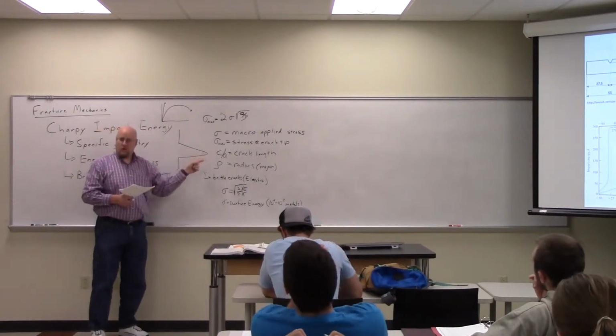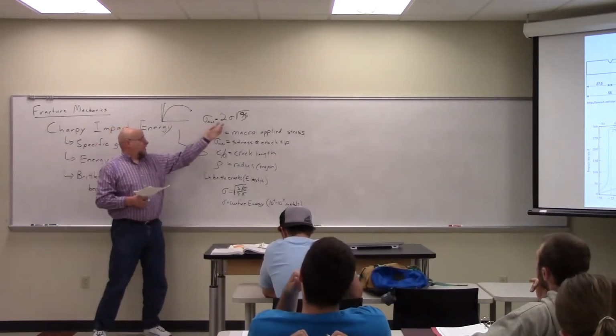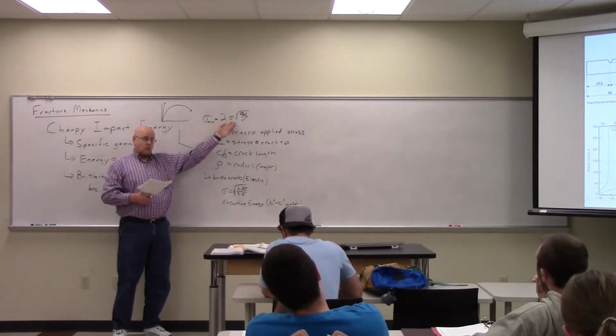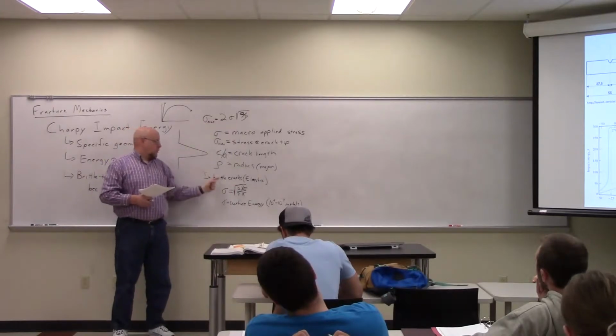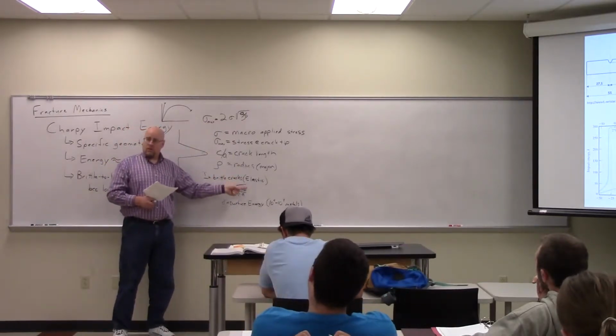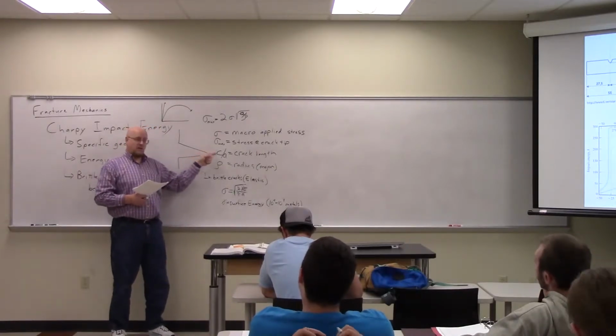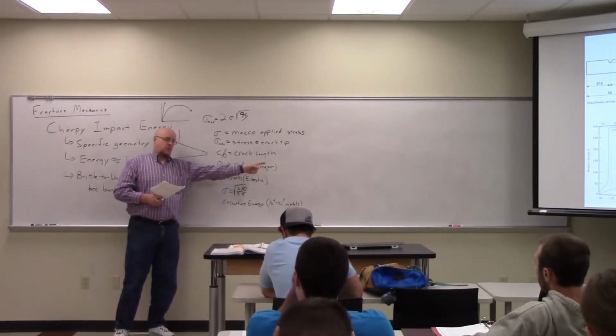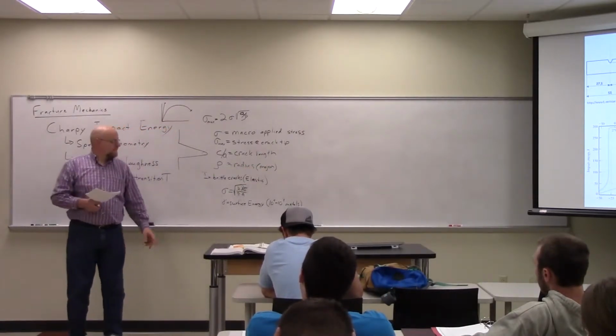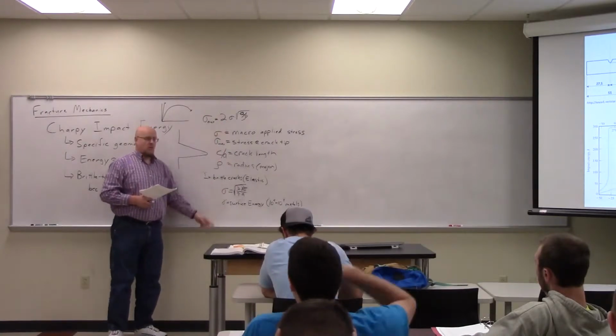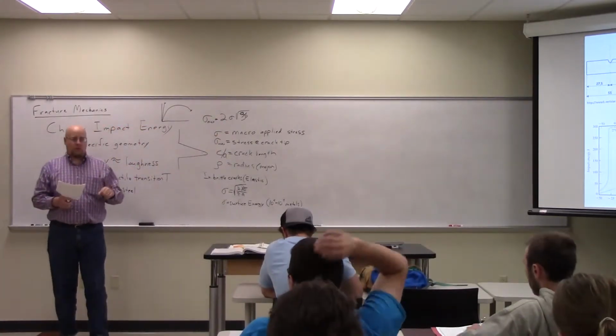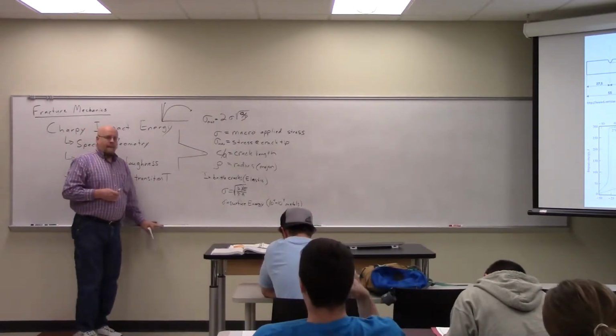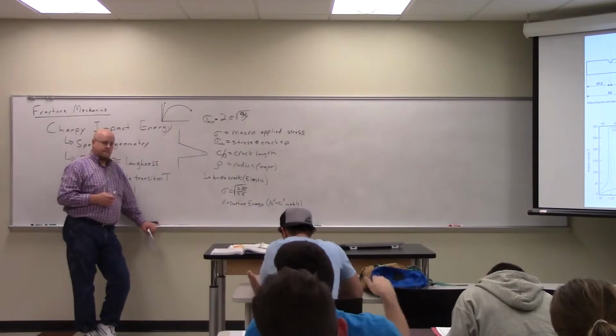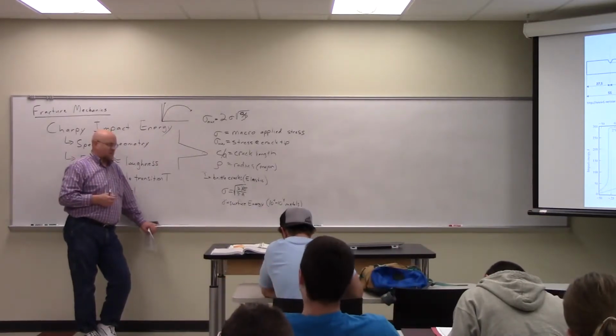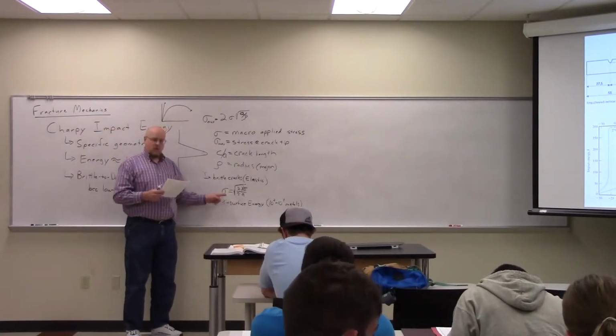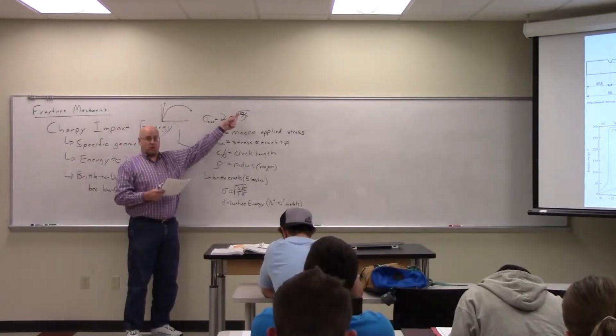So I have a pre-existing crack in a material. That pre-existing crack will concentrate the applied stress to a larger value. As soon as that concentrated value exceeds that necessary to cause the crack to propagate, basically as soon as that stress is big enough to break the bonds out here, it will propagate through the material. So as soon as sigma max equals the square root of 2 gamma E over pi A, we'll get crack propagation in an elastic, brittle material. If you maintain your applied stress, then that crack should go all the way through the material, because A is getting bigger. As A gets bigger, the necessary stress gets smaller and the applied stress gets bigger, so it just becomes worse on both ends.